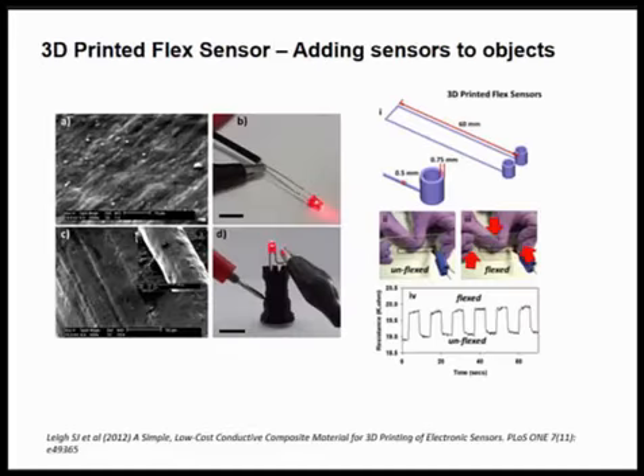3D printed flex sensors, so sticking with the FDM or thermoplastic technology. This time using carbon black embedded in a thermoplastic matrix. Again, solution dispersion. In this case, the filament we feed into the system was actually rolled by hand. So there's no compounding, it was entirely solution dispersed, solvent evaporated, and essentially just rolling about a meter's worth of filament by hand. It was enough to get us test filament to run through the process.